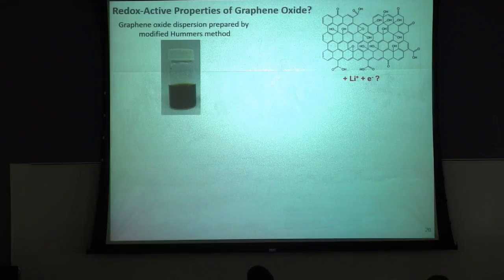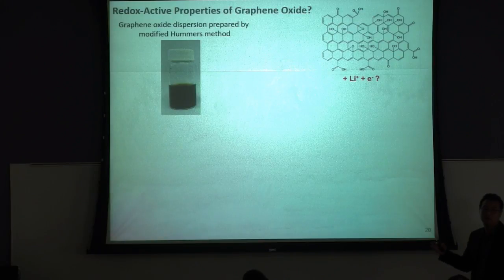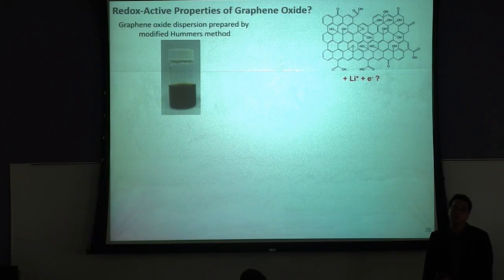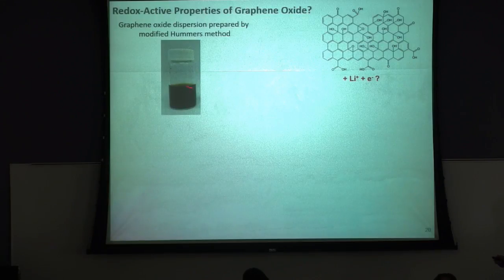So these days, we can prepare graphene oxide from graphite using the chemical oxidation process called the modified Hummers method, right? So we can prepare a large scale of graphene oxide from graphite. So this is the graphene oxide solution, basically graphene oxide dispersed in water, which is prepared by the modified Hummers method in our lab. So then, if we see the surface chemistry of this graphene oxide, it is a little bit dirty. There are many different types of oxygen functional groups, so it is not well defined. But we can expect some kind of redox reaction between this kind of oxygen functional group and lithium ion, right?